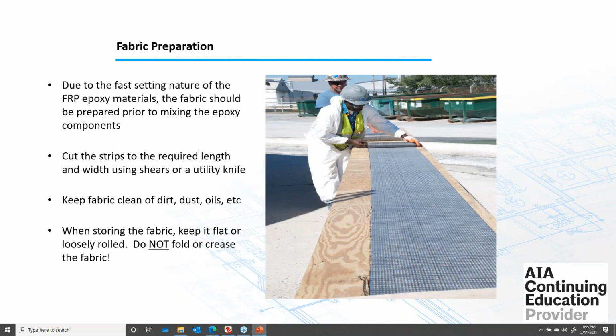Due to the fast setting nature of the epoxy materials involved in the FRP system, the fabric should be prepared prior to mixing the epoxy components. So the contractor has to cut the strips to the required or designed length and width using a sharp tool. Also keep fabric clean of dirt and contaminants, and always avoid folding or creasing the fabric.